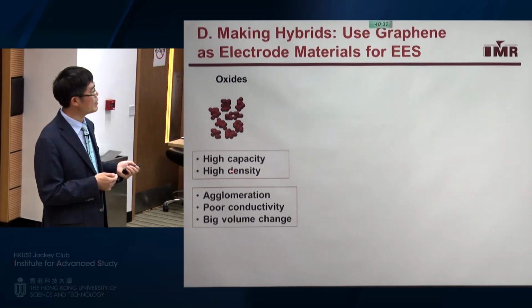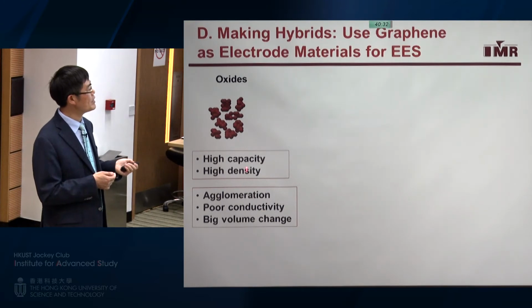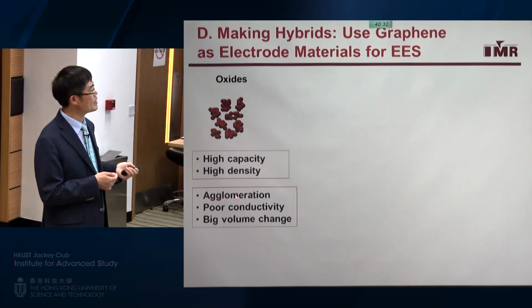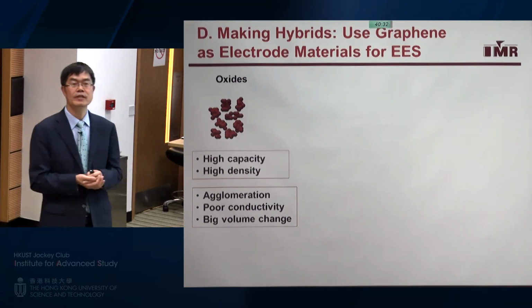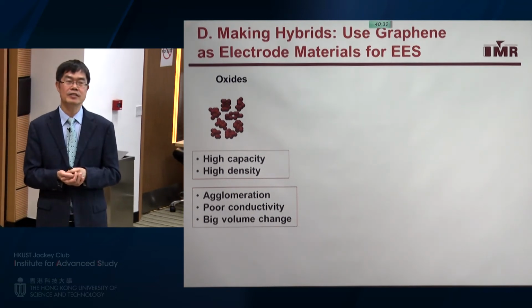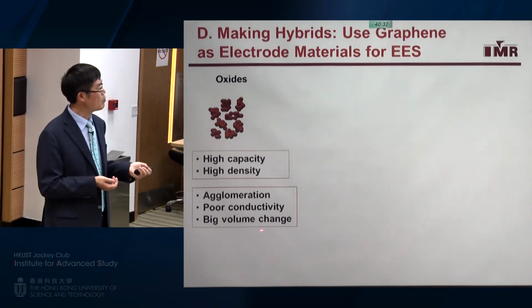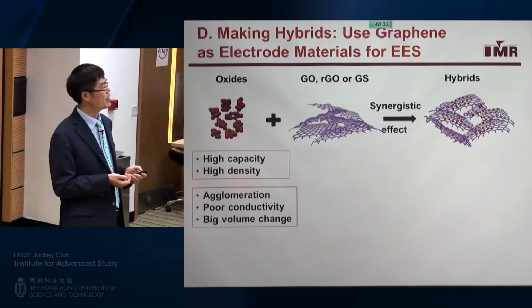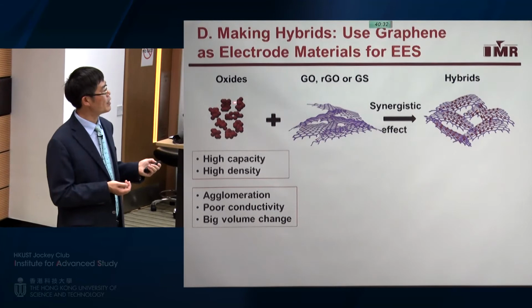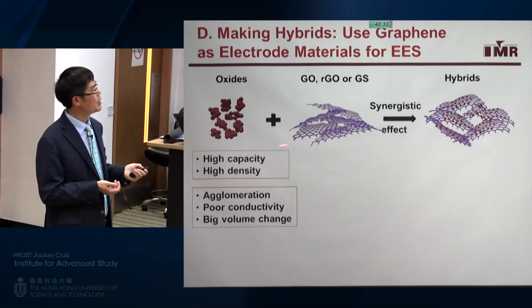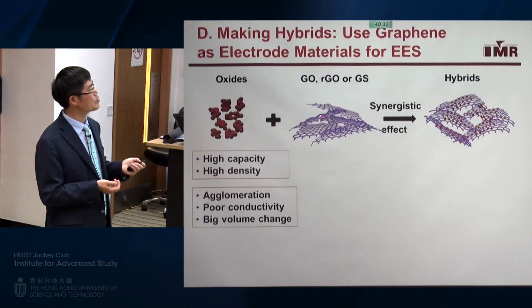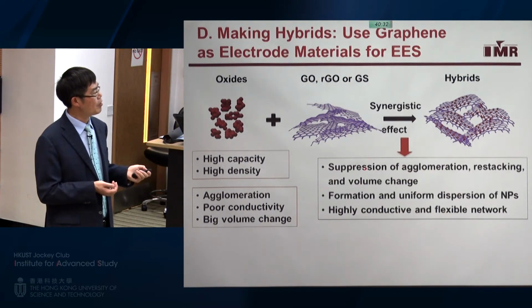We know oxides have very high capacity, but oxides are also very easy to agglomerate and have very poor conductivity. Many oxides are insulating, and also have big volume change during charge and discharge. So when we have graphene, we proposed to incorporate those two materials together to suppress the agglomeration and volume change of the oxide, and also to suppress the restacking of graphene.